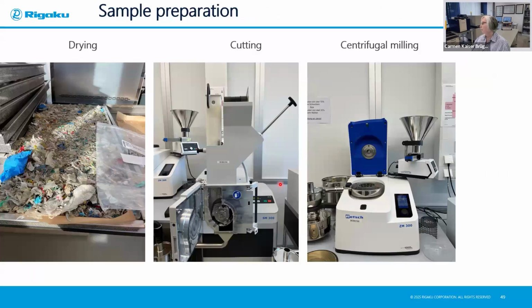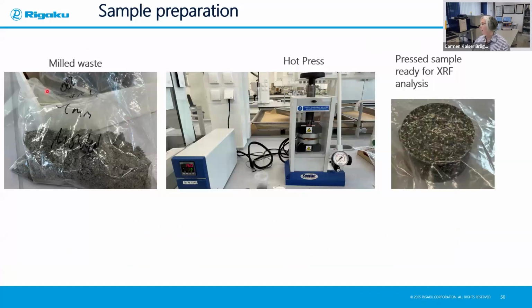Okay, so here I want to show you a little bit about how you can prepare this kind of sample. So here you can see an example of waste, like municipal waste. Many industries, even the petrochemical industries, can extract oils from here, and they also need to measure these samples. Here, for example, you can see a lot of different colors and a very heterogeneous sample. So, of course, the first thing we need to do is to dry the material at the correct temperature. And then this dried material can be passed through a cutting mill that you can see here. And then after it's been shredded and cut, we can split the material and then undergo what we call centrifugal milling, so that we land up with a bag that looks like this.